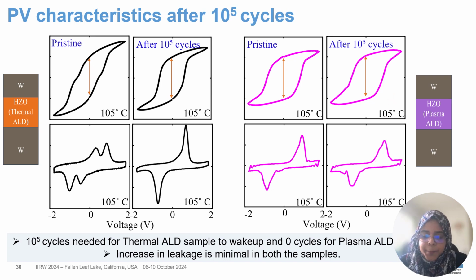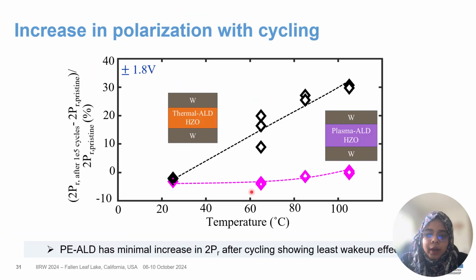Now we have tried to understand how much polarization is increasing after cycling in both of these devices. So here the x-axis is temperature, and the y-axis is the difference of 2Pr, or the difference of polarization, before and after 10^5 cycles with respect to the pristine state. So this will tell us how much polarization we are increasing after 10^5 cycles compared to pristine state. And this also is a measure of the wake-up effect of both the devices.